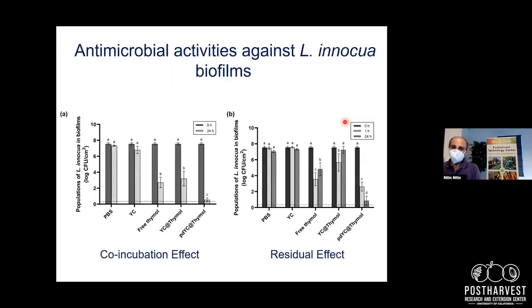Here I'm showing an example of it where this material shows significant inactivation of Listeria biofilms on model plastic surfaces in this case. And what was very intriguing to us was the residual effect, that even if we just co-incubate this in the vicinity of it, it prevents the formation of biofilm. And its effect is quite persistent. Like if you use free thymol, it does inactivation early on, but after 24 hours, the Listeria start growing back. But with this agent, you are able to maintain the persistent concentration in that area for a longer period of time. So even after 24 hours, you have significant inactivation in this case.